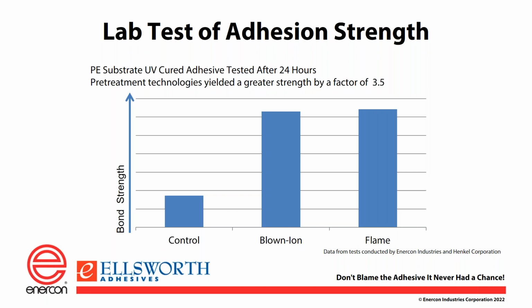And this was a lab test that we did with a polyethylene with a UV cured adhesive. And after 24 hours, you can see that the bond strength more than tripled from our control using both the blown ion, which is the plasma, and the flame plasma. And this happened to be a Henkel adhesive that we use in the control test. This is just kind of showing you the difference in bond strength that you'll get after treatment.